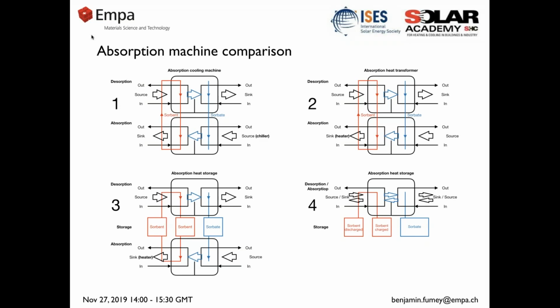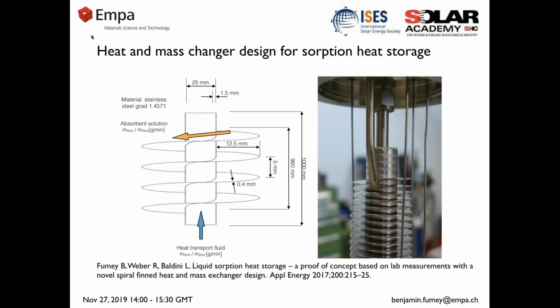For this reason, we find for the liquid sorbents the tube bundle falling film heat and mass exchanger as used for chillers and for heat pumps is not ideal. So we've gone towards developing a spiral finned tube heat and mass exchanger, also reported in the below publication. And one of the main things that we reach here is a much longer exposure time of the sorbent, which is needed to be able to move towards that equilibrium line to be able to get those high energy densities.